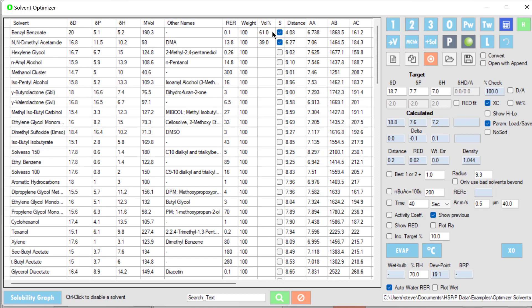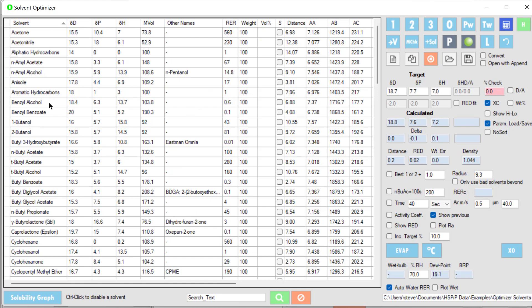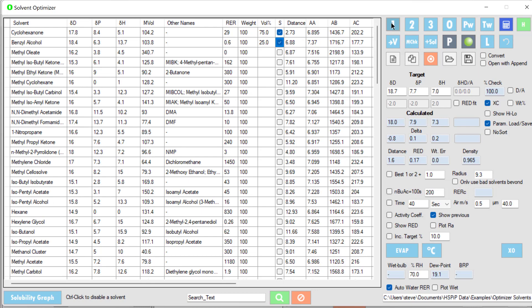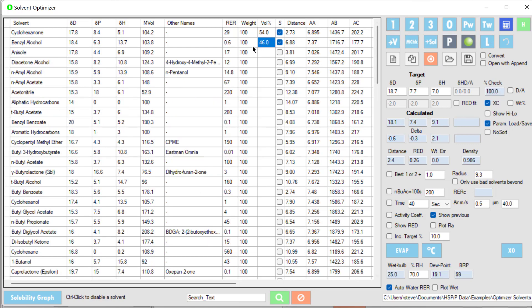Let me unselect those and sort again. Let's say I'm really keen to use benzyl alcohol, a really nice solvent for various reasons. Which one solvent combined in any proportion with benzyl alcohol would be a good match for PLA? I click the one button and find that a 25-75 blend with cyclohexanone is a very good match with just a distance of 1.6. But suppose I want to use 46% benzyl alcohol for some good reason. I click the one button again—if you really want to use 46%, then cyclohexanone is still the best co-solvent and the distance is a bit further. You can start to find good solvent blends via this technique.